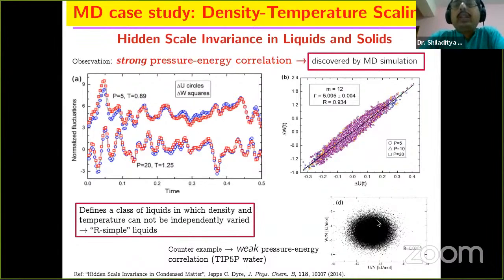Now I can show you that this is not true for all liquids. This is a complex liquid, you can say, and this is not true for any liquid. So it is a counter example. The same plot of pressure versus energy, the same scatter plot, looks like a circle or a black hole, round-shaped, which means that the correlation is very weak, maybe 5% or so. Yeah, 0.5%. So this is water. So here is a model where there is weak correlation, and here is a model with strong correlation.